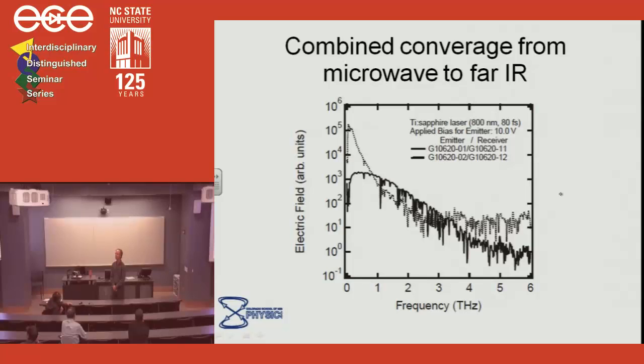How practical is something like this for remote sensing? So for longer distances, you're coupling your field very close, but can you do feet, tens of feet? Oh, well, for the near field, we were doing that because we wanted very localized material properties. But as you saw on the quasi-optical bench, the sources and receivers are well over a meter apart. And there's no reason to think you couldn't have them 10 times as far apart. It's a matter of collimating the beams and having sensitive detectors. The 40 gigahertz interferometer that I showed at the beginning that we built ourselves, we've used out to distances of 100 meters.